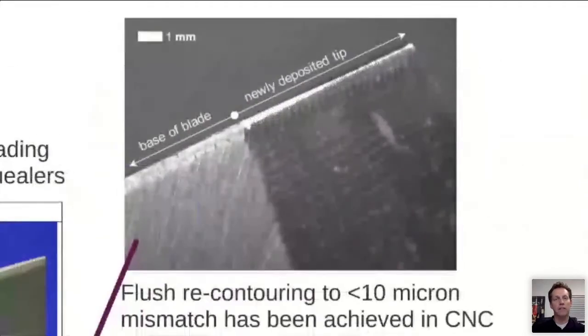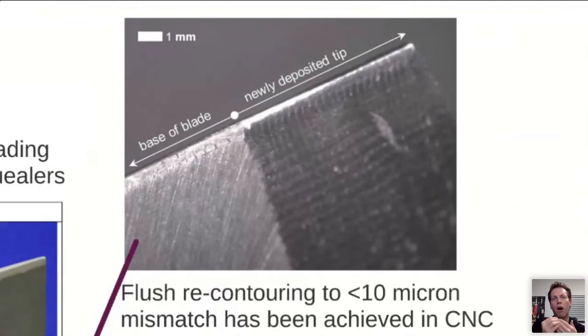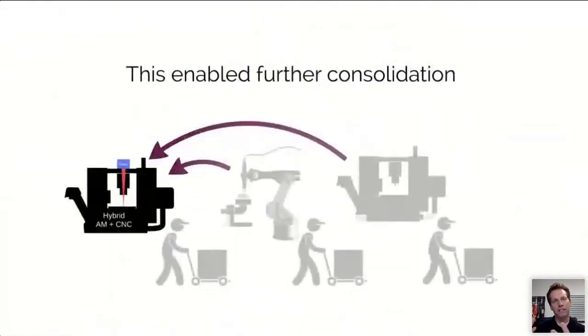This is another blade, an aerospace blade. And this really highlights that blend machining, which is at the end when you're going to try and get the mismatch between the original and what you've added to be as small as possible. And the tolerance for that is very tight, typically less than 20 microns. And with a well-calibrated machine, we've found that that can be hit within plus or minus 10 microns, sometimes better. So very exciting. So once these had been all proved out in a piecemeal fashion, then they were able to be brought all together. So then parts could completely be diverted.